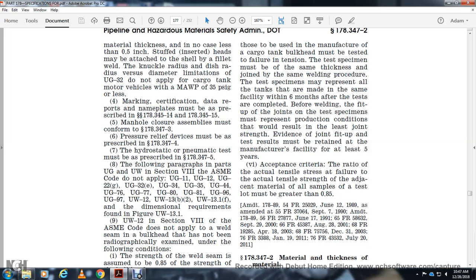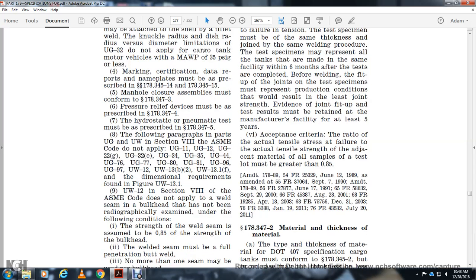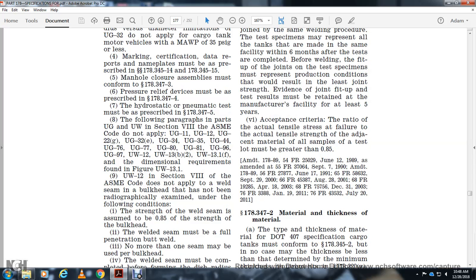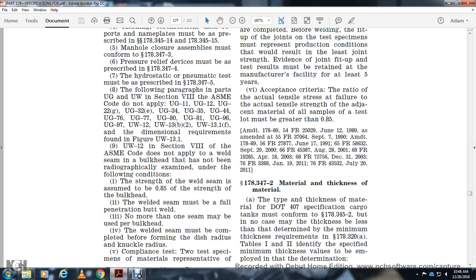UW-12 of Section 8 of the ASME code does not apply to a welded seam bulkhead that has not been radiographically examined under the following conditions. The strength of the welded seam must be assumed to be 0.85 of the strength of the bulkhead. The welded seam must be a full penetration butt weld. No more than one seam may be used per bulkhead. The welding seam must be complete before forming the dish radius and knuckle radius.